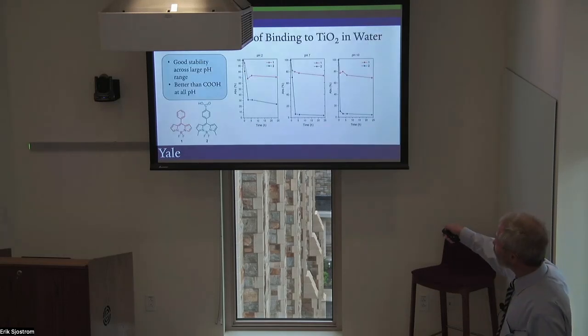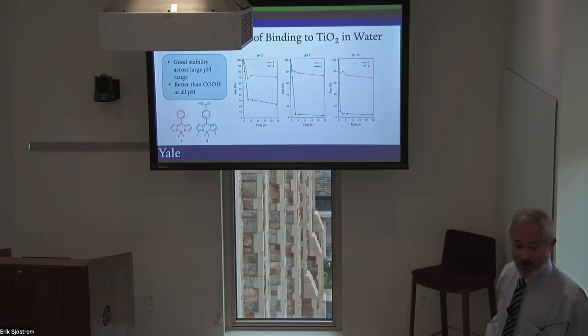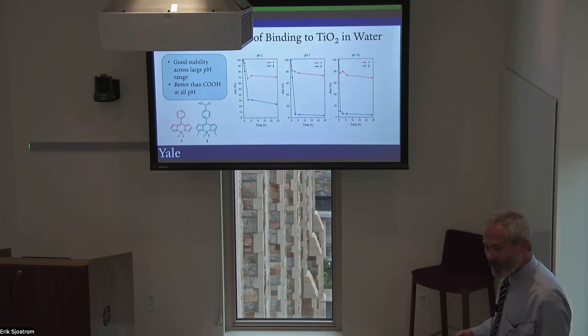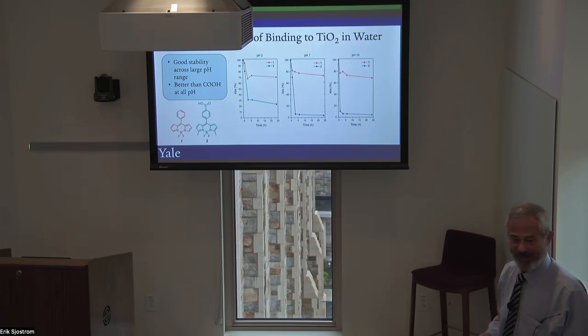And this is just showing the stability in water. If we soak a carboxylic acid linkage at pH 2, 7, or 10, it rapidly comes off. It's a little more stable under acidic pH, but not stable at higher pH. On the other hand, the Brudvig is bound pretty stably, even over a pH range from 2 to 10. So this is now a really interesting situation because we've got a very stably coordinated anchoring group, but it's also a dye. So it serves two functions at once.